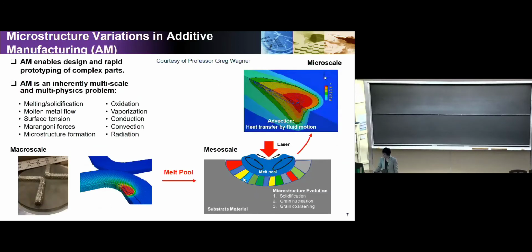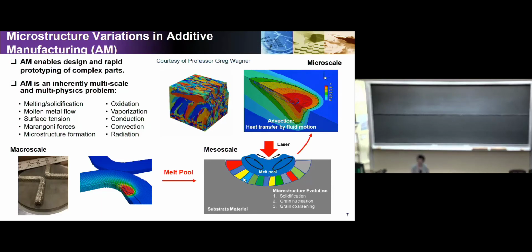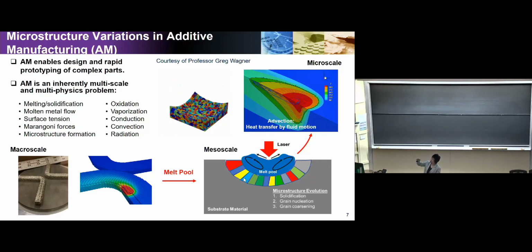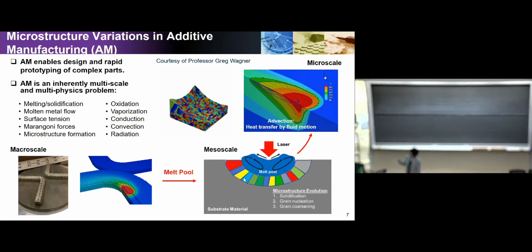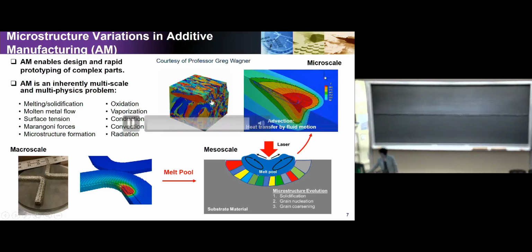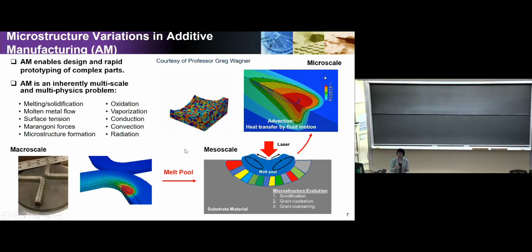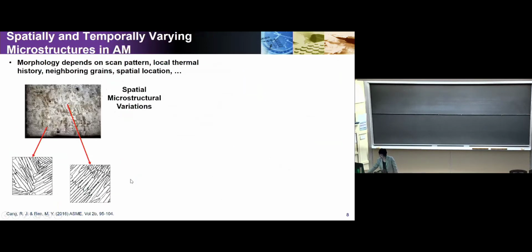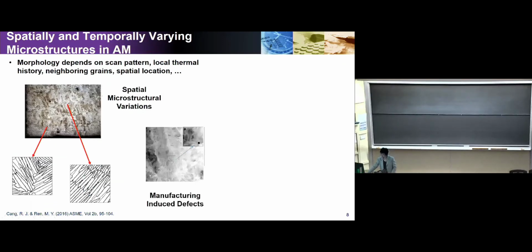Another motivating case explains why it's so important to consider the microstructure variation from one location to another. That's an additive manufacturing process where my colleague Greg Wagner's group has been developing simulation codes that start with three sets of simulation, from the tool path generation to the melt pool, very much fluid dynamics based, and at the end to the microstructure at each different location. So what you see here in the picture is actually the grain structure at different locations. Those kinds of simulation are very expensive, and there's a need to build a model that can quickly assess the behavior at different locations. And this microstructure variation can be spatially coupled, and there's also another type of structure we need to consider, called defects.